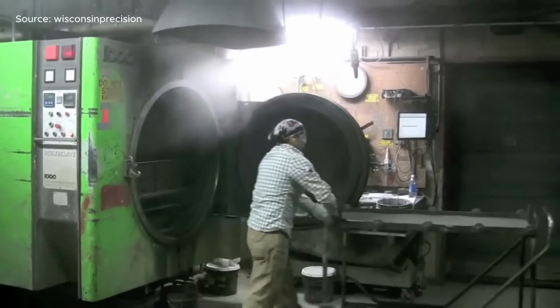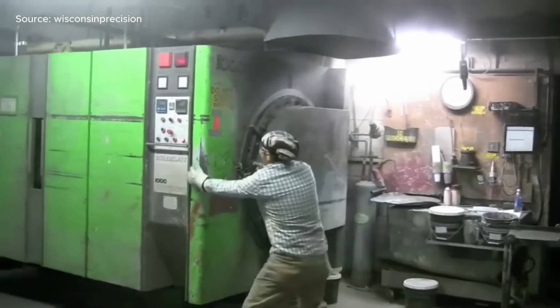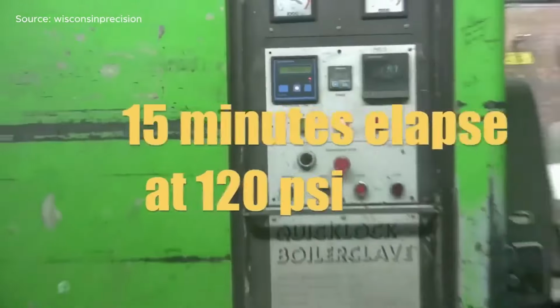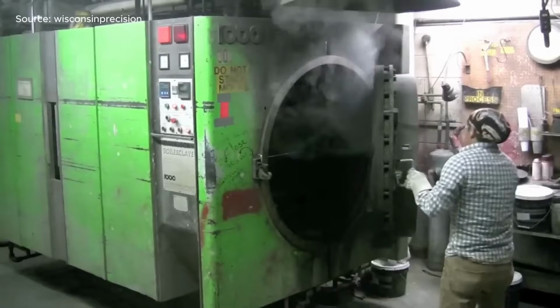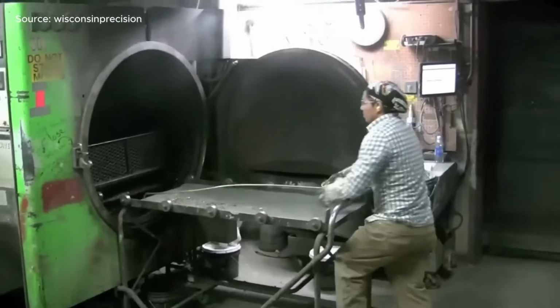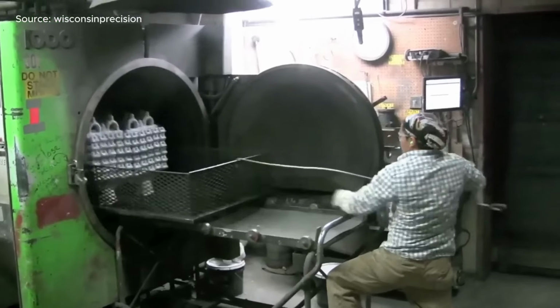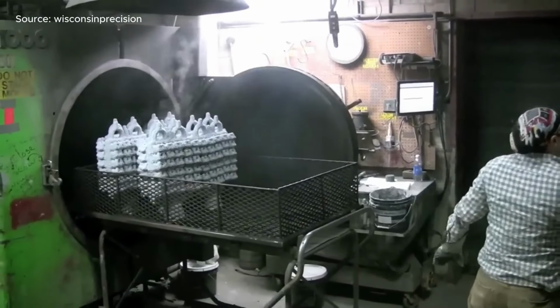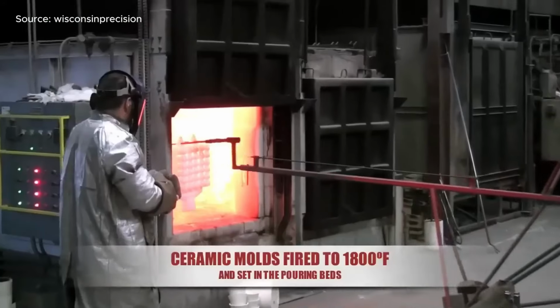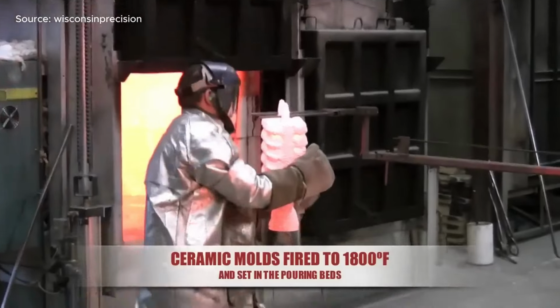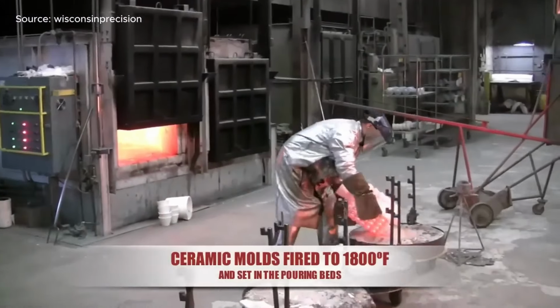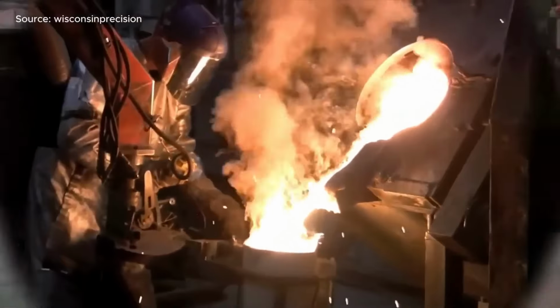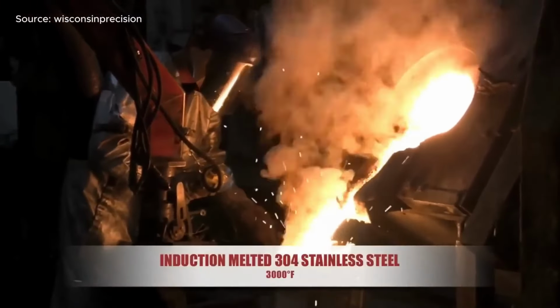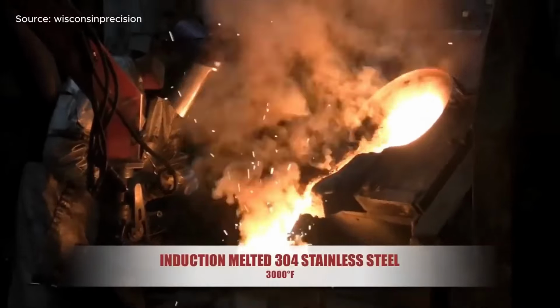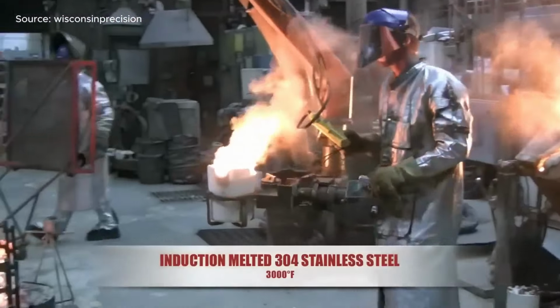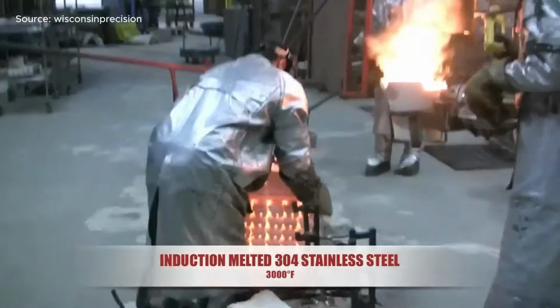Wax removal. The ceramic molds are placed inside a pressurized steam vessel to remove the wax. The process takes approximately 15 minutes at 120 psi, ensuring complete removal of wax while maintaining mold integrity. High-temperature firing. After wax removal, the molds are fired at 1,800 degrees Fahrenheit to strengthen the ceramic shell. This step also eliminates residual wax and prepares the mold for metal casting. The fired molds are then set into pouring beds.